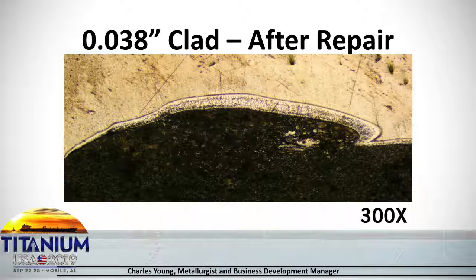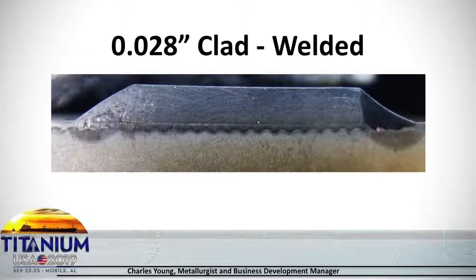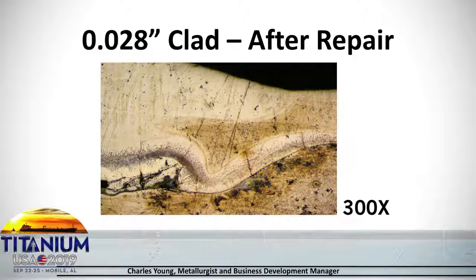And going down to 028, again, you see a major heat affected zone in the steel itself, and you can see that the 028 is almost just above the ripple on the explosive bonded surface. But you can see, especially over here, that you're getting weld disruption in that zone. And if you look at it here, you're getting some voids in here. You're getting some oxidation. You're also getting some iron into that titanium, so that you're almost disrupting that bond. So you're going to have a problem there with this bond eventually.